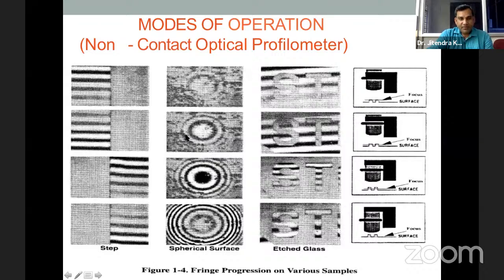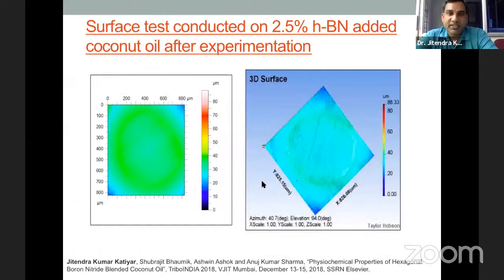In spherical surfaces, like if you want to check a wear ball after a four-ball test, you can see that the fringes form in a spherical nature. In that way also, if there is distortion in the ball, the fringes show some cavity or some wear that happened over the ball surface. And if you want to get some engraved structures, the fringes form first on the top surface and then the depth. In this way we get the 3D image using the 3D optical profilometer. I have done this work, and this is the wear ball surface.